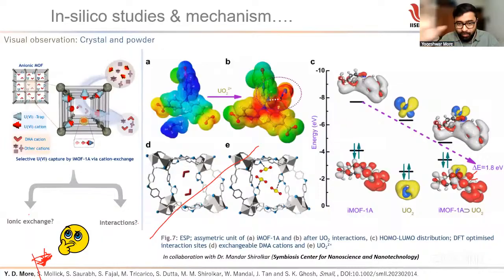So going further, we have done the thermodynamics, XPS and all. By using theoreticians, we tried to understand the mechanism behind it, particularly what is exactly happening. We now know which nitrogen is interacting with what. So we did a simulation for that, basically DFT and ESP structures. What we found is that these Lewis basic nitrogens here are interacting with the DMA cation. Now they are forming weak interactions with the uranyl cation, and they are replacing 2 DMA, and these sites are occupied by the uranyl cation, and hence you can see in this energy diagram where the HOMO-LUMO distribution can be seen effectively.